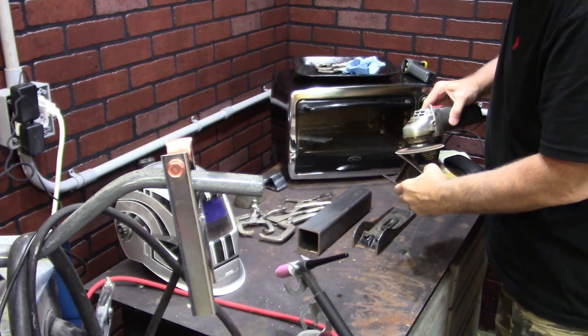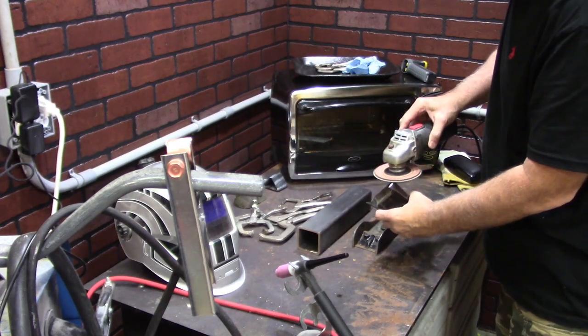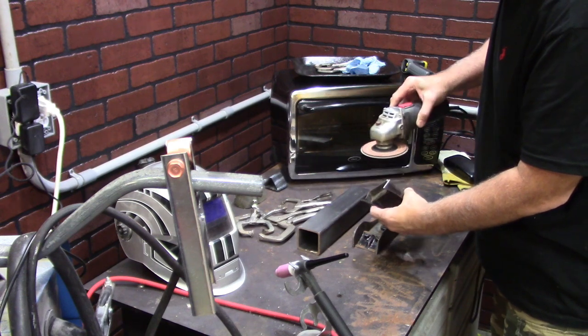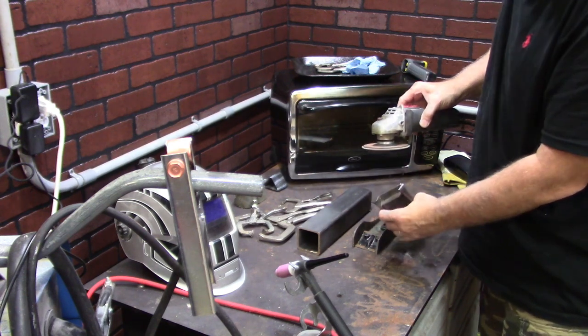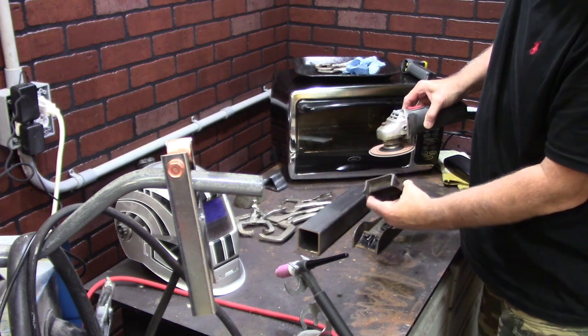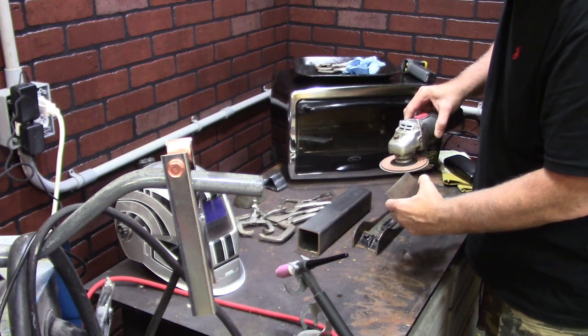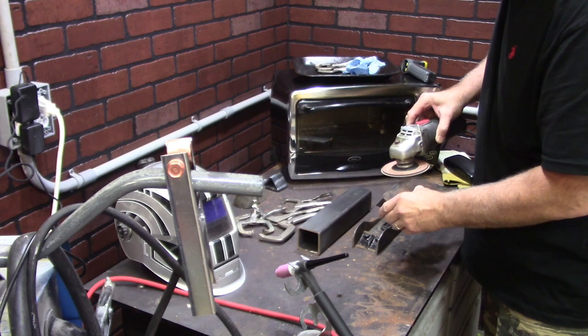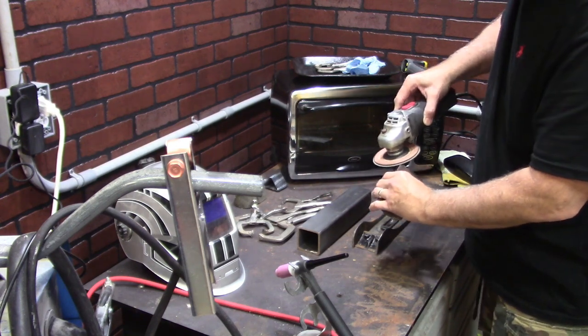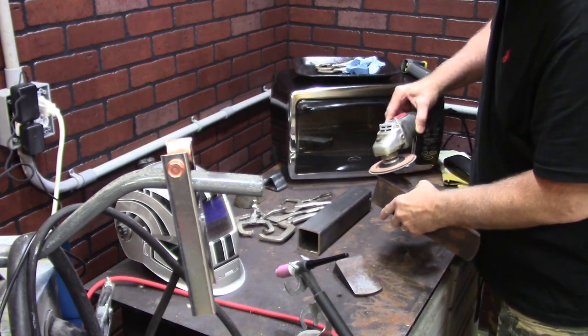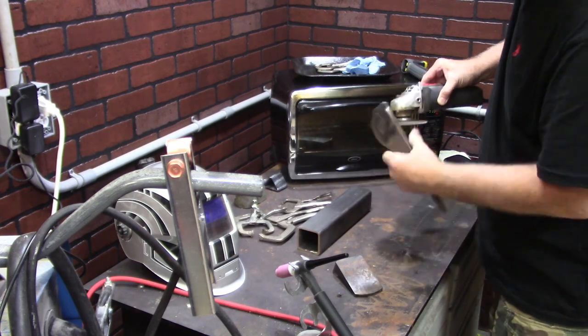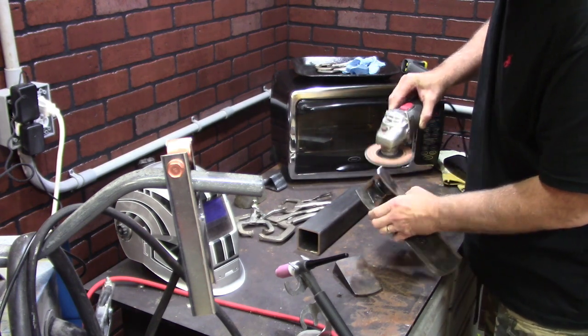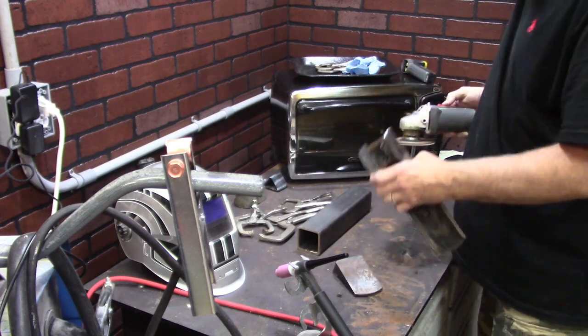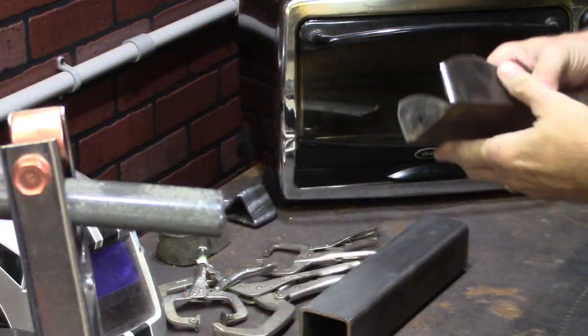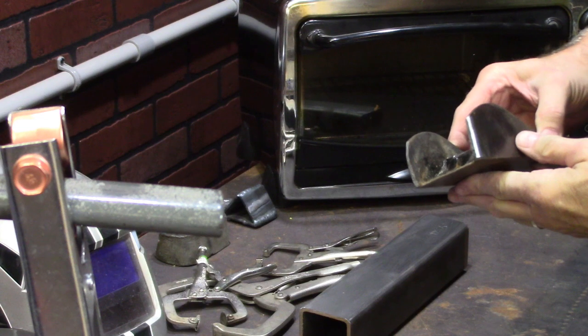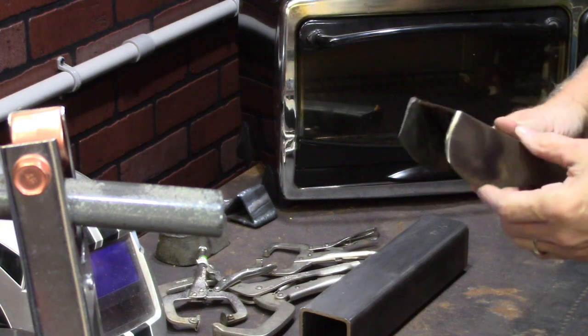Okay, so what I'm doing here is I'm using a flap disc, and I'm going to bevel the edges of the web of that plane. They're only 1/8 inch thick at the top of that web and about 3/16 near the base. That's all the cast I have to work with. So I've got to put a bevel on it so I get good penetration. At the same time, I can't go all the way through. I have to have that fracture line of the casting so that I can put it back together and it'll lock in proper alignment. Here you can see what I've done.